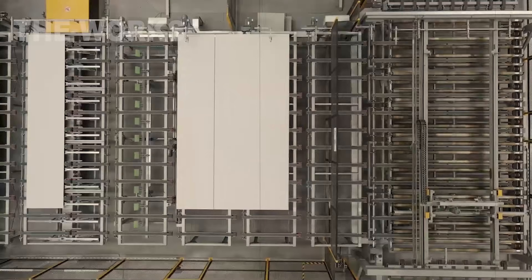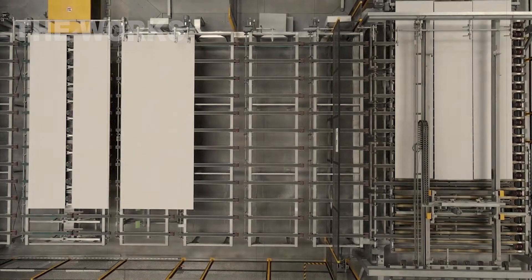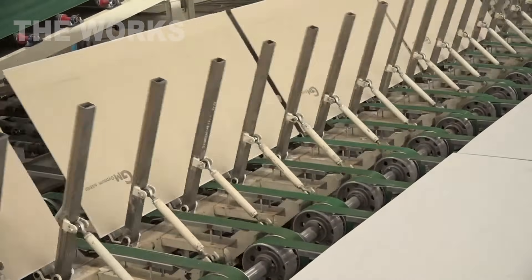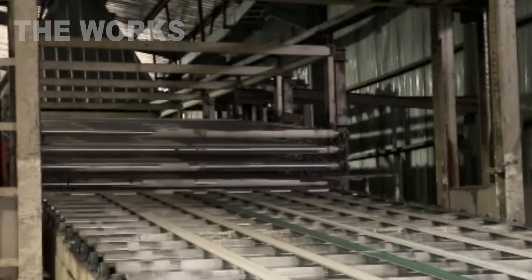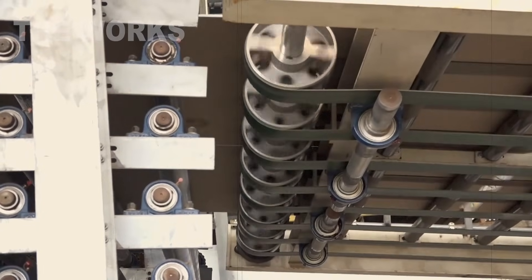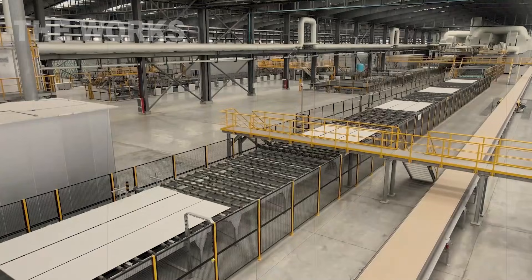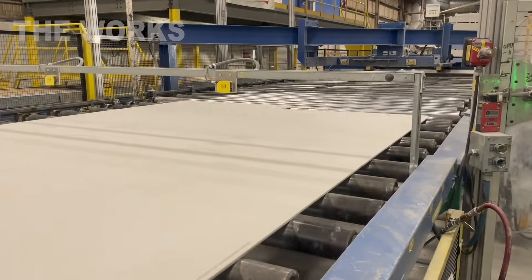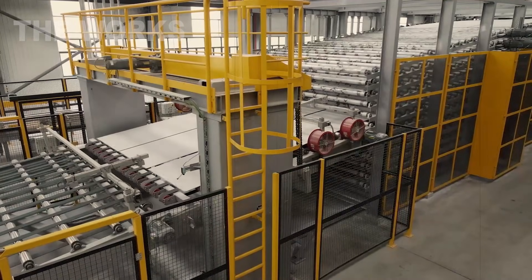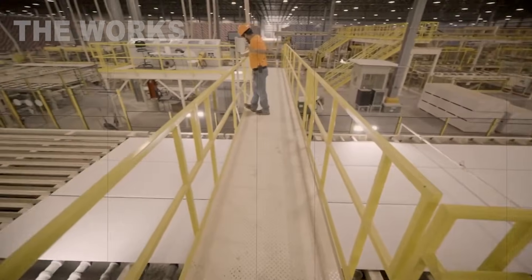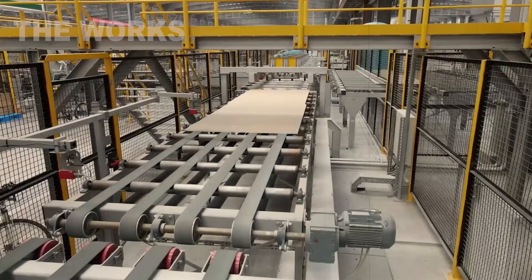A special device flips the sheets and feeds them into the most massive structure in the factory: a multi-deck drying kiln. This is a giant labyrinth consisting of several levels, each of which is a conveyor. The drywall sheets slowly move along these levels back and forth, traveling several hundred feet inside this huge furnace. Hot air circulating inside gently evaporates the excess moisture. The temperature is very carefully controlled — only the free water needs to be removed, without damaging the crystal structure of the gypsum itself. This process can take about an hour. At the exit of the dryer appears a perfectly dry, light, and strong sheet of drywall.